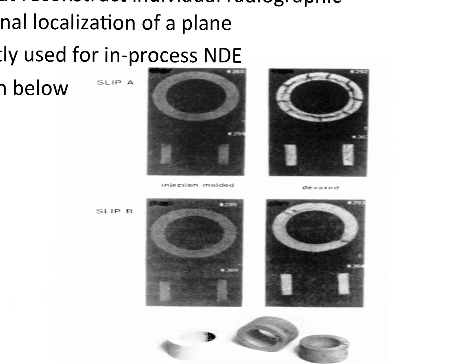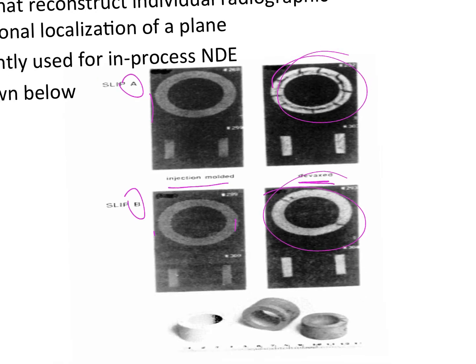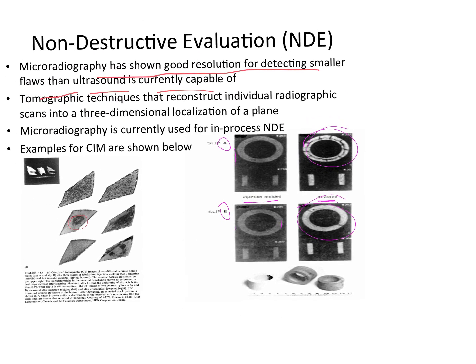And this is just showing you a couple of injection molded ceramics made from slip A and slip B, which refers to the liquid. They're both injection molded, and you do an X-ray scan on them. They look the same. You don't really see much of anything, but then you remove the binder, de-waxed as it says here. Then you see a bunch of cracks show up in slip A, and only a couple cracks show up in slip B. So this is the kind of thing that you can use to say, well, there's a problem with slip A. We need to go work on that.